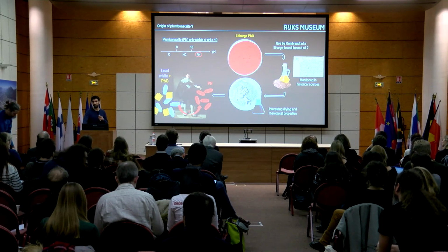Absolutely. So obviously the experiments we did in the lab were with pure litharge, but we do think that a key parameter is if the litharge is entirely dissolved in the oil or not. So far it seems that the experiments are showing that you need to have, let's say, still a remaining grain of litharge for this crystallization to kick in and start from this litharge.